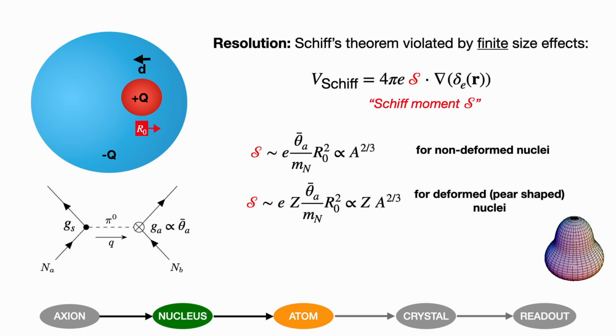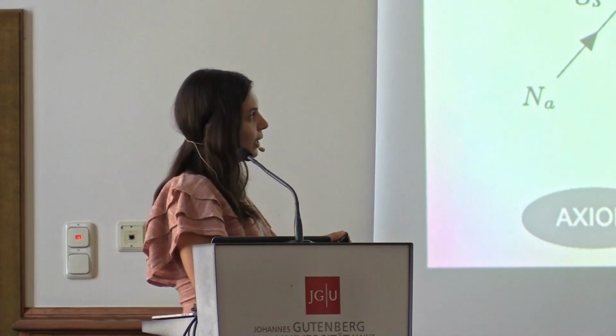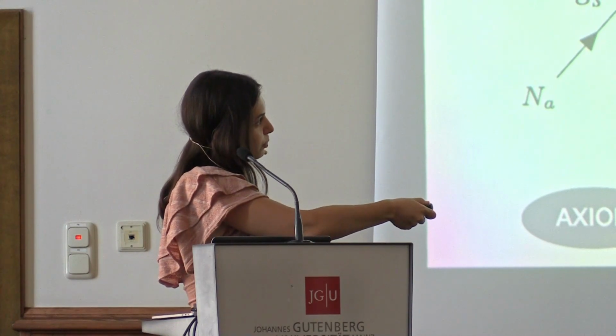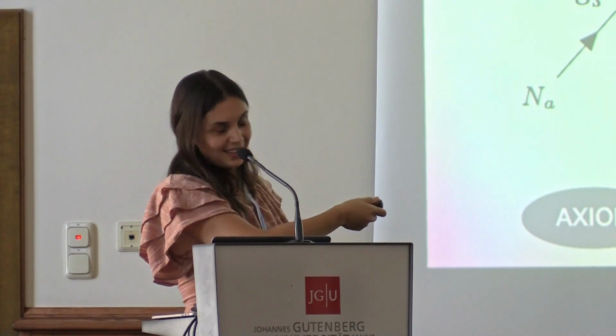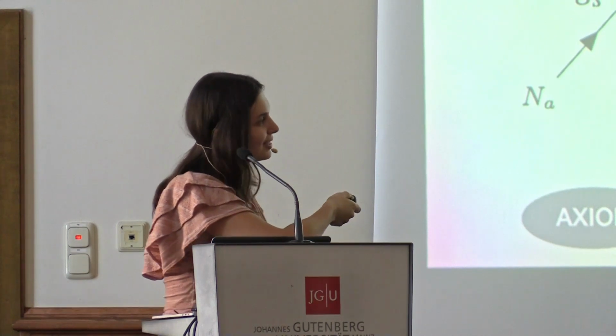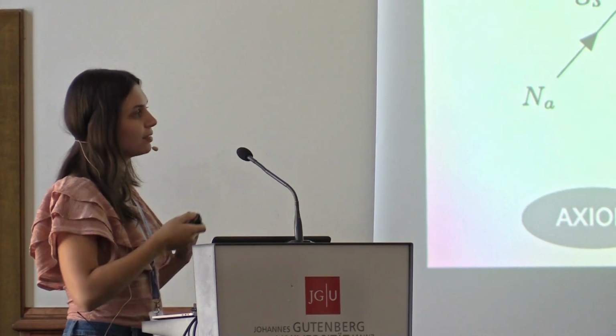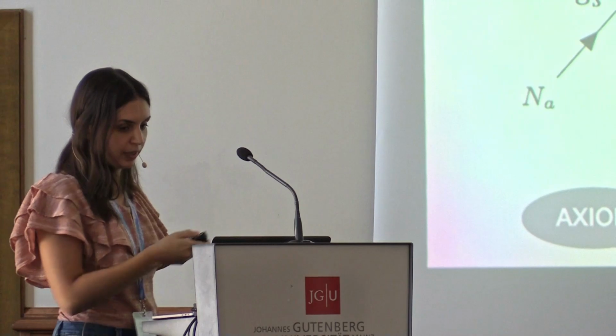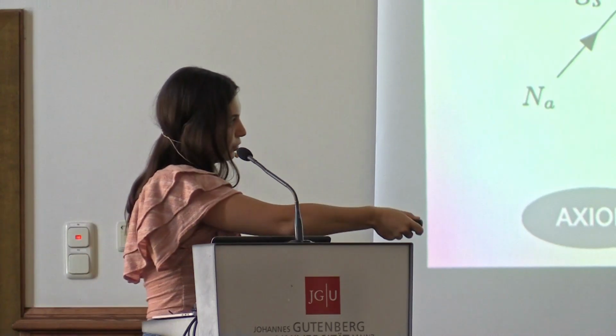So the first scaling here, oh, I've lost my pointer, here, is for a spherical nucleus. However, there are these special nuclei, they're usually rare earth elements or possibly very heavy radioactive elements, but we're more interested in the stable ones, where there's an enhancement by a factor of a number of protons. And that enhancement is beyond the scope of this talk, but essentially depends on some kind of collective vibration of all the nucleons here in these intrinsically deformed nuclei.